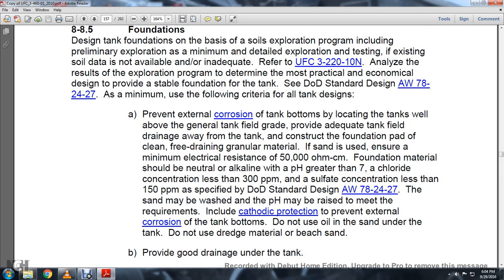To prevent external corrosion of the tank bottoms, locate the tanks above the general tank field grade and provide adequate tank field drainage away from the tank. Construct the foundation pad with clean, free draining granular material. If sand is used, ensure a minimum electrical resistance of 50,000 ohm-cm. Foundation material should be neutral to alkaline, pH greater than 7, with chloride concentration less than 300 ppm and sulfate concentration less than 150 ppm as specified by the Department of Defense design AW78-24-27. The sand must be washed and the pH must be raised to meet the requirements, including cathodic protection to prevent external corrosion of the tank bottoms.